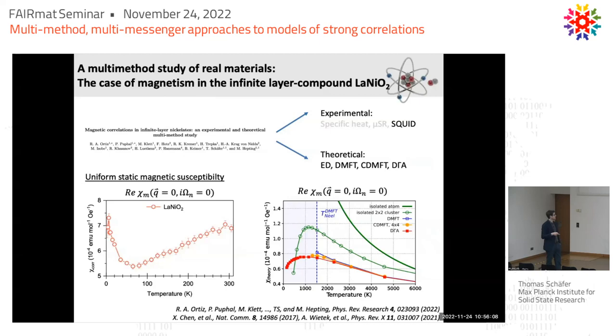And there it turns out that the DMFT, which is the starting point for the DΓA, orders. And you cannot get rid of this ordering without the Moriya correction. This is a bit of a problem, and it is not fully clear how to introduce this in a true multi-orbital system, I would say. But there are some developments also with Georg in Hamburg, who is going in that direction. But I think a bit of thought still has to be put in there.